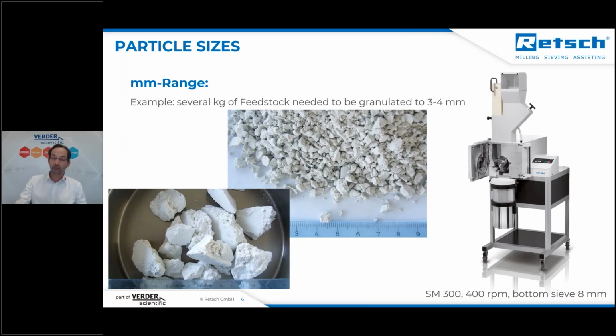And so we used the cutting mill for this purpose to grind the feedstock down to 3 to 4 millimeters. And with a bottom sieve of 8 millimeters, it is quite easy to create a size of smaller than 4 millimeters. But the difficulty again was to avoid the fine powder. And there the cutting mill SM300 is a good choice, because this machine allows you to set the revolution speed of the rotor from 100 to 3000 RPM.